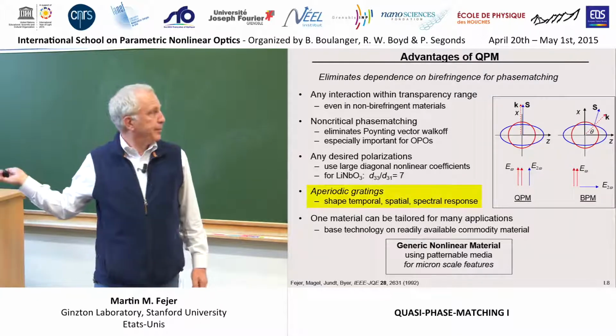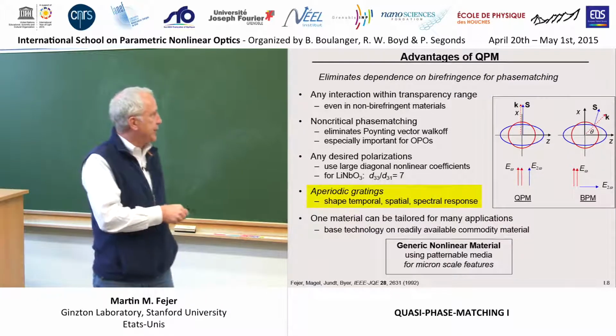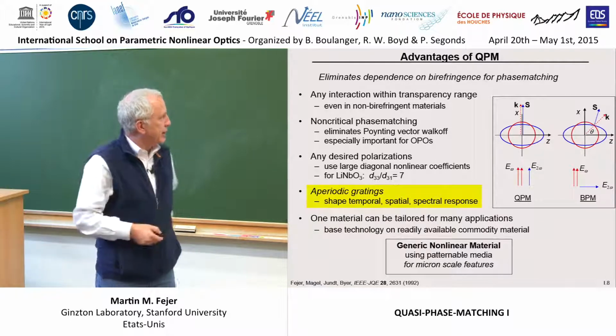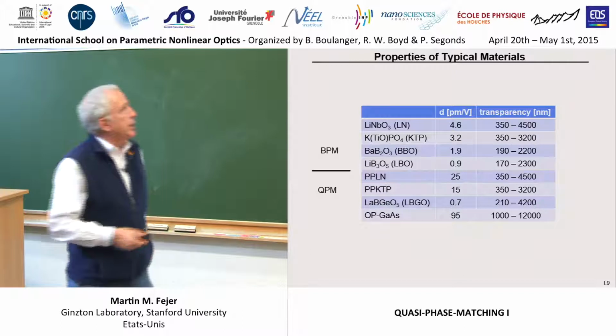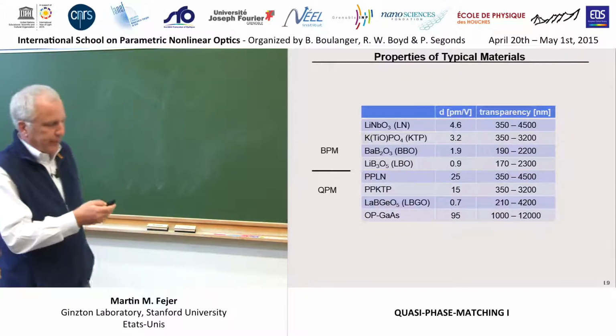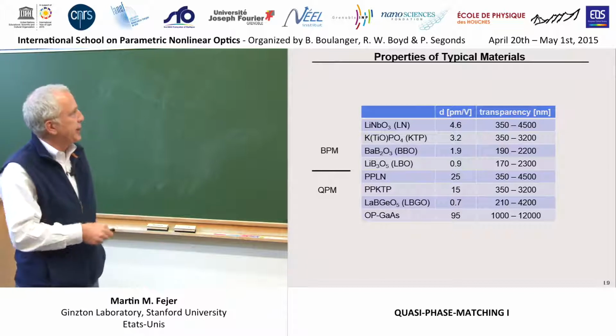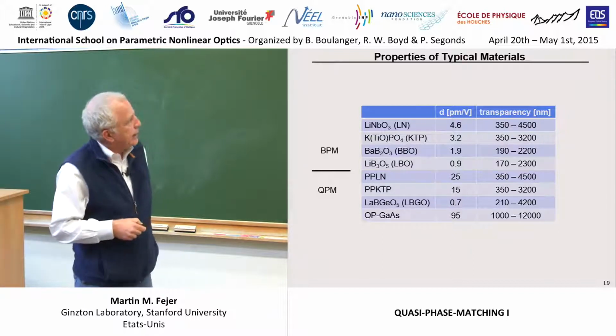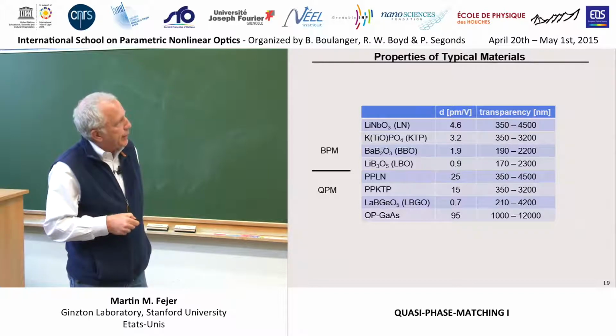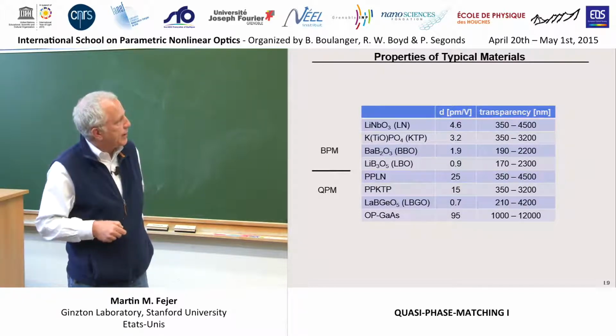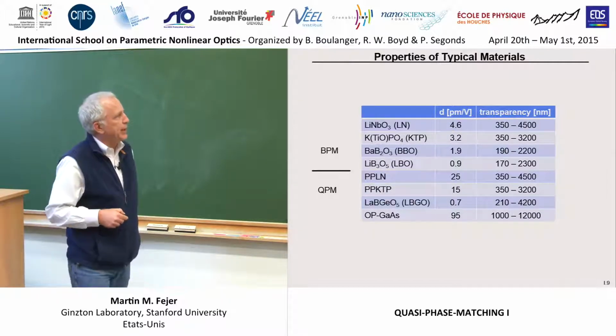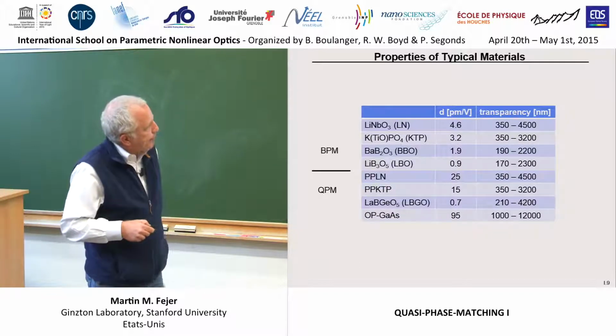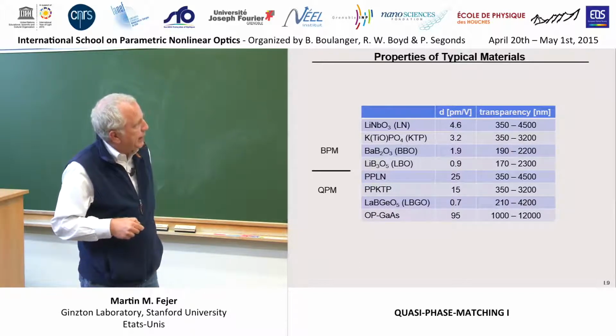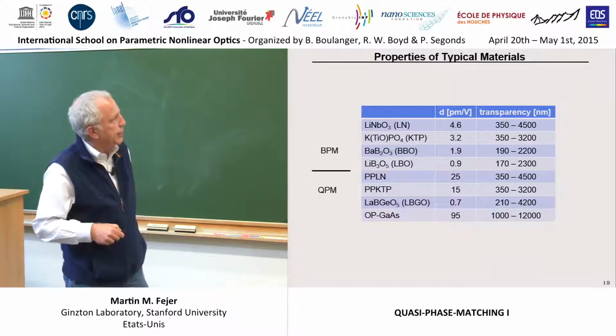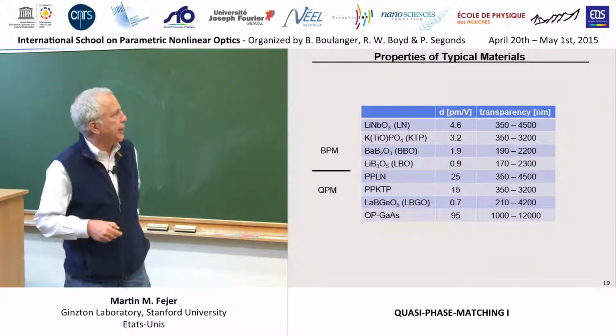Okay, so like I said, I will emphasize in large part these kind of techniques because, well, I'll explain why later. Just a look at some typical properties of a few commonly used birefringently phase-matched materials versus quasi-phase matched materials. For example, lithium niobate, the nonlinear coefficient used for birefringent phase matching is substantially, as we discussed, smaller than the one for quasi-phase matching. And if you look at the borate materials, they're an order of magnitude smaller in nonlinear coefficient than lithium niobate